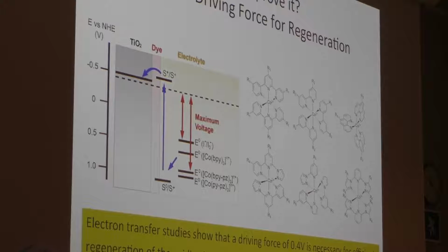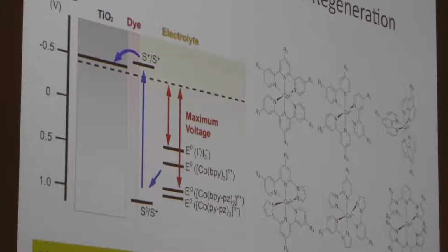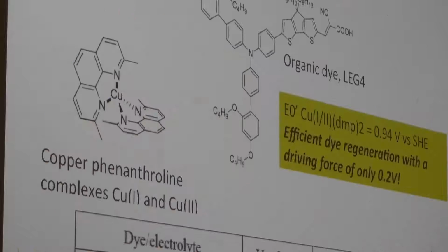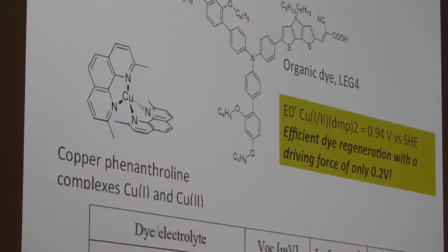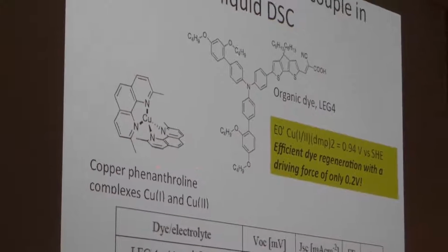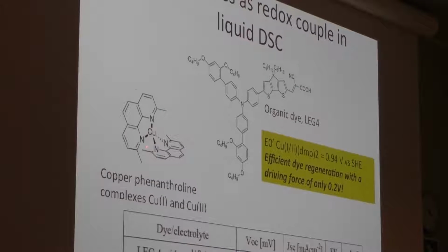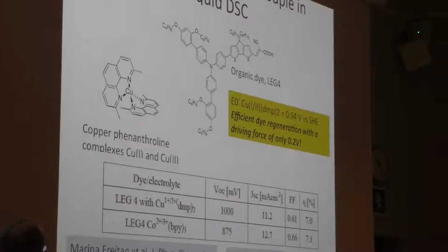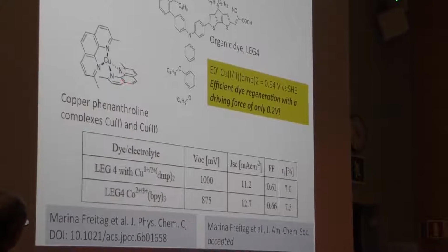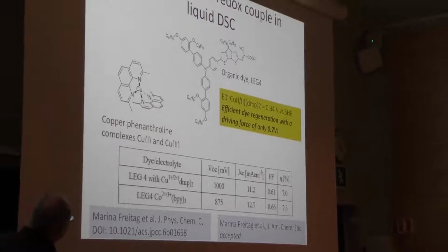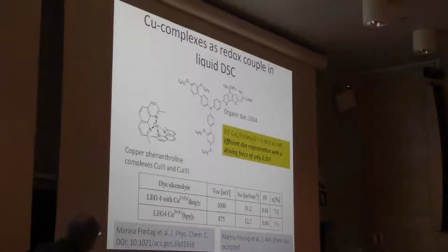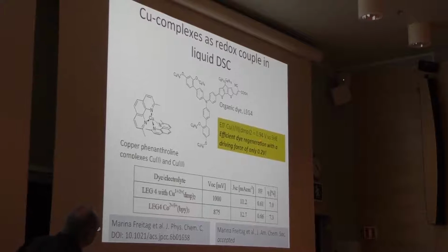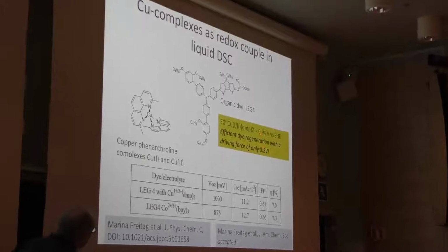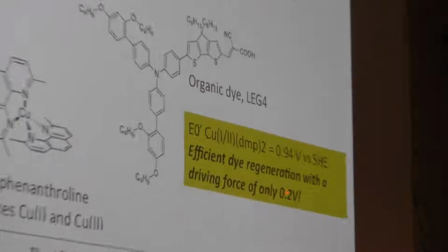So what we dream about is to find a redox system where we can regenerate, let's say with 0.2 volts or something. That would be your dream target. And we maybe have one system which we are excited about now, and that's copper phenanthroline. It was the starting point, published by Peng Wang in China first at 7% efficiency. We took that up, and what you see here is that the redox potential is very positive. The driving force now is less than 0.2 volt.